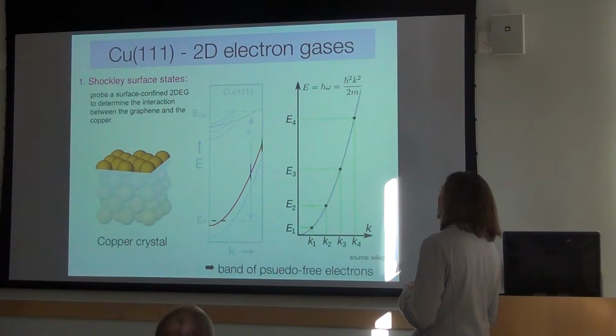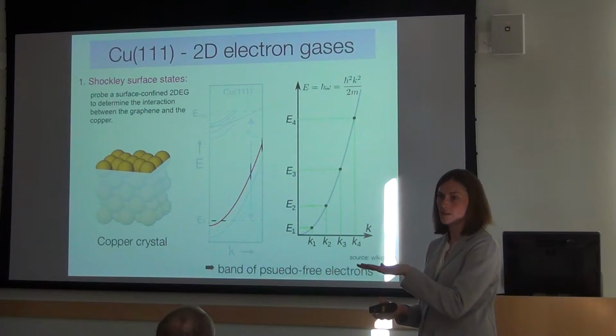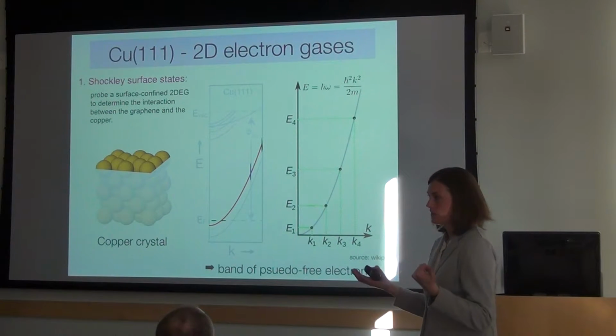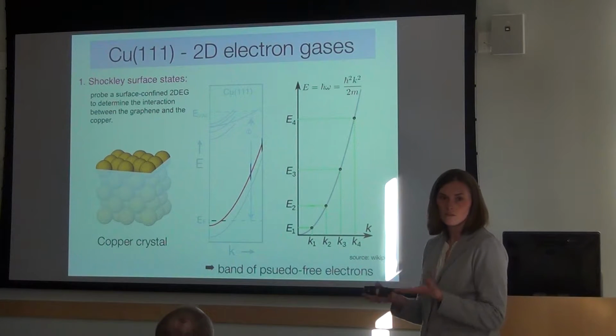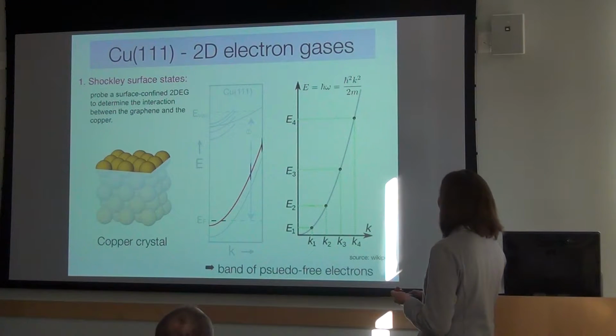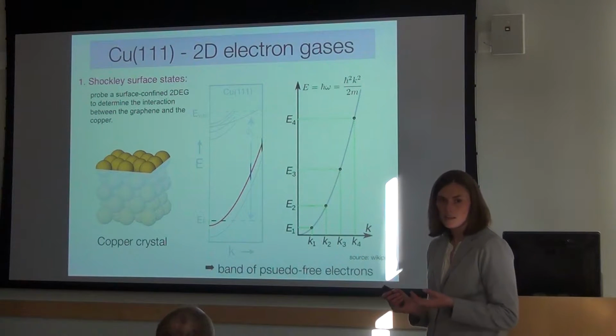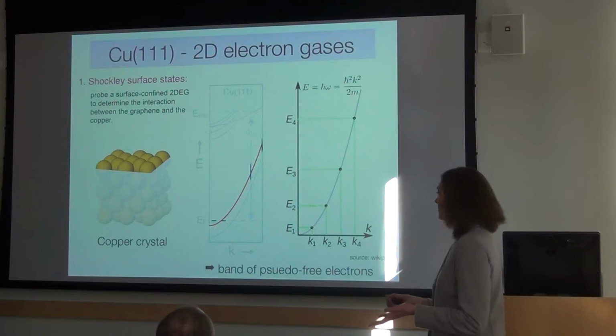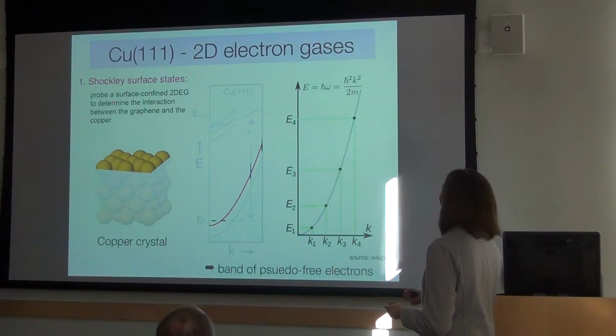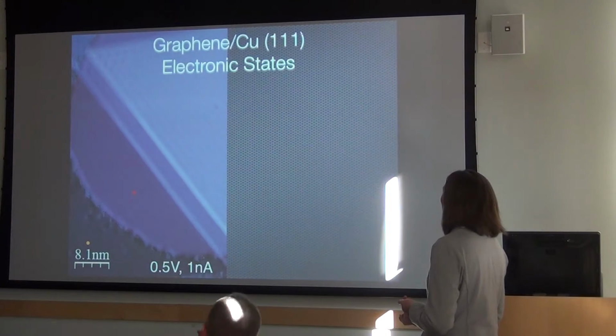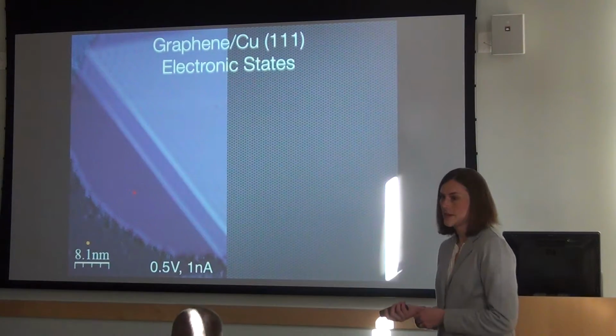This appears because the actual surface interface creates different boundary conditions that allow for the creation of the surface state. What's interesting about it is that it doesn't overlap with any of the other states in the copper crystal. So basically it's a band of almost free electrons, and that's what it's compared to over here. These are electrons with some mass, some effective mass. And we can measure the surface state with STM.